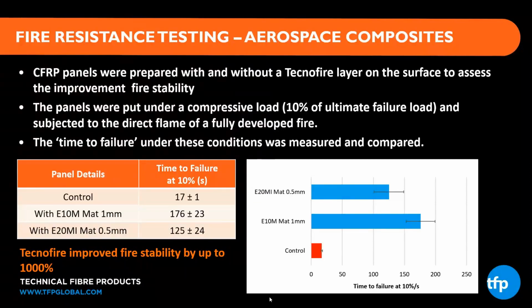So if we look at the table on the left, you can see from the control panel, it's failed after 17 seconds under compressive load. So the panel has been put into this severe fire event under 10% of its ultimate compressive load very, very rapidly. The panel has exceeded the glass transition temperature of the epoxy resin used in the composite. That resin has no longer been able to transmit the stress on the fiber, so that the panel has failed under compressive load.